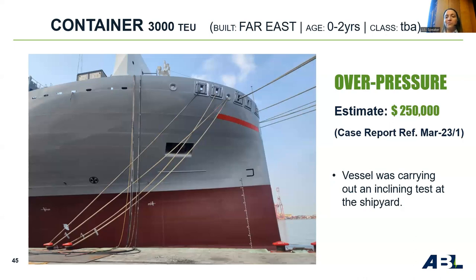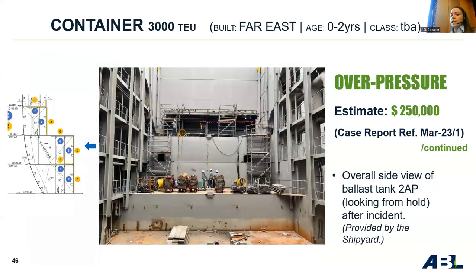Alas, during pumping of water into the number 2 ballast tank, the crew noticed that the outlet pressure on the ballast pump reached 7 bars, which is 7 atmospheres, whereas it shouldn't normally go above 2.5. So immediately they stopped the pump and went to investigate. They found that the inner plating of the ballast tank bulged outwards, a rather clear sign of overpressurization. Here you can see the yard has already started cropping out the upper section of the bulged plating.